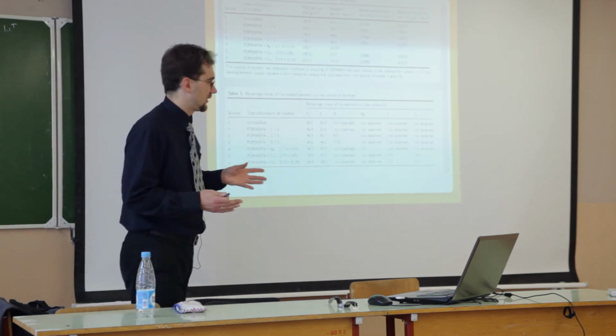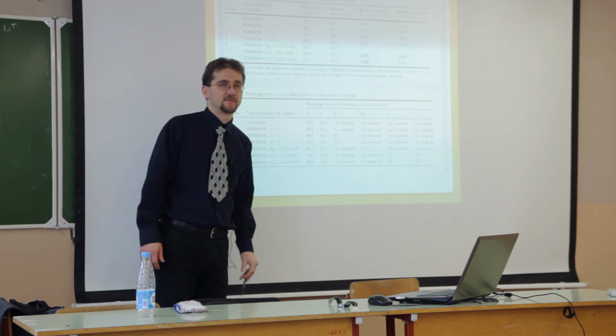Of course, always the same problem: how to control the surface with thin layers. We used for this a special apparatus which can give us information about the elemental structure only on the surface, a couple of micrometers in depth.